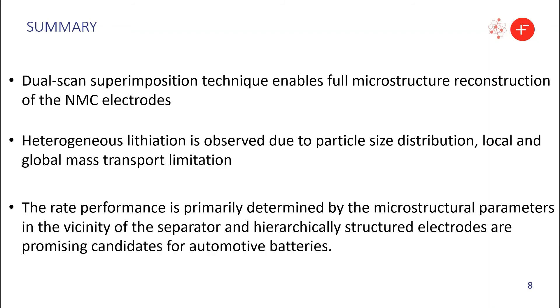Here is the summary of my presentation today. First, the dual scan superimposition technique enables full microstructure reconstruction of the NMC electrodes. Heterogeneous lithiation is observed due to the particle size distribution and local and global mass transport limitations. Finally, the rate performance is primarily determined by the microstructure parameters in the vicinity of the separator, and hierarchically structured electrodes are promising candidates for automotive batteries.